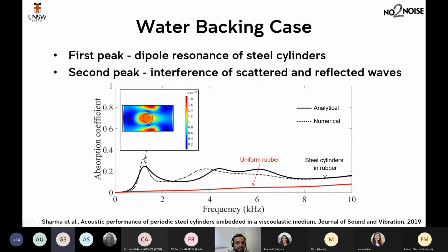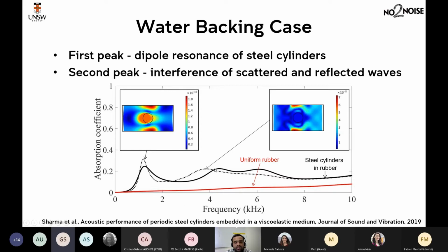This peak is due to dipole resonance of hard inclusions in your soft medium, which dipole resonance, as I have talked about before, is just an oscillation of your inclusion in the direction of sound propagation. So back and forth oscillation in this direction at this frequency. The second peak here. So remember, we have water backing here. We have water on both sides, here as well as here.